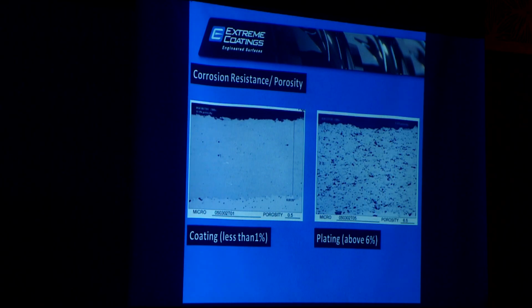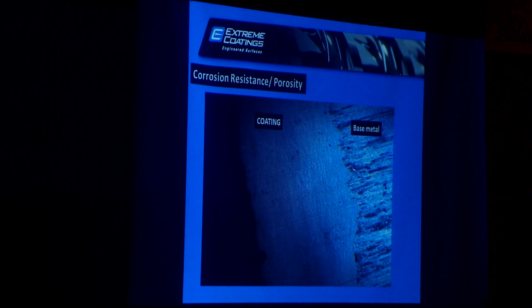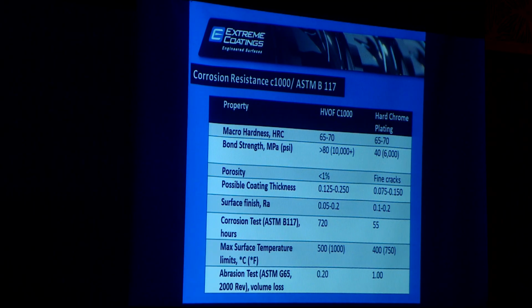Let me explain what I'm trying to say here. On the left hand side, what you are seeing is a coating surface which does not have high porosity, while on the right hand side is a chrome plating surface which has lots of porosity. That means acid can enter up to the base metal and start pitting, while that will not happen in the coating. This is the surface of the coating. You can literally see there is hardly any porosity or crack on the surface of the coating. The chrome plated piece started pitting after 55 hours, while the coated piece lasted for 720 hours. That's the beauty of the corrosion resistance with the carbide coating.